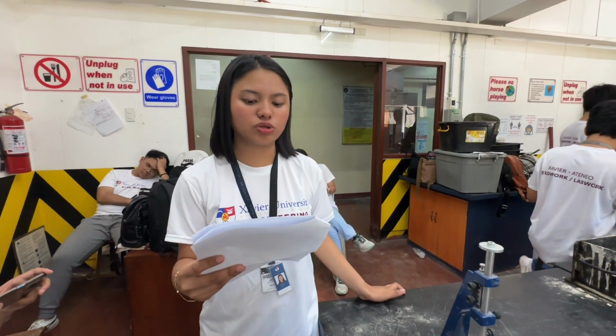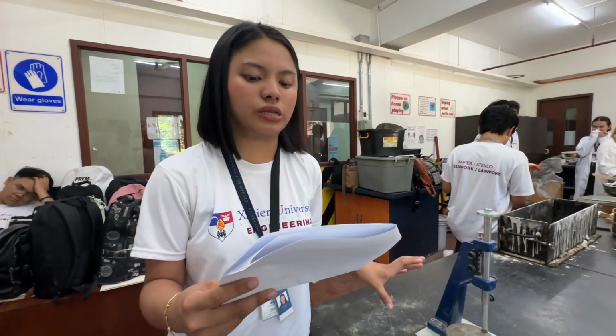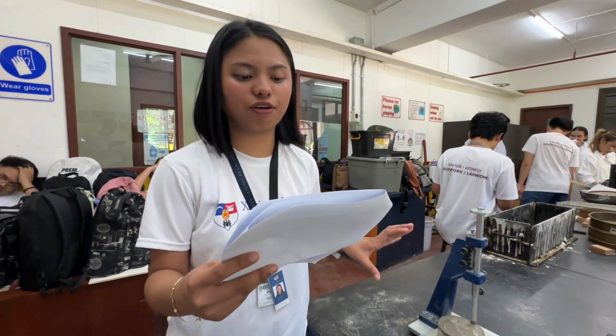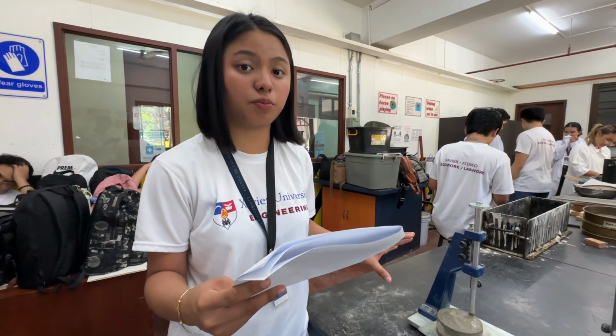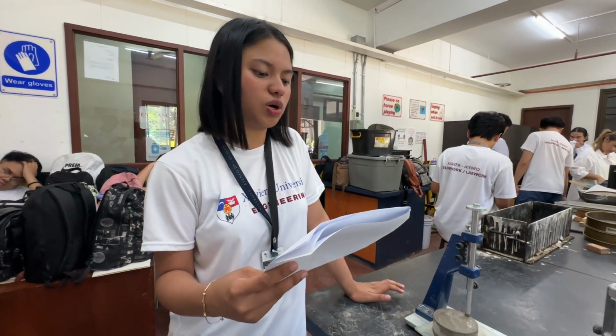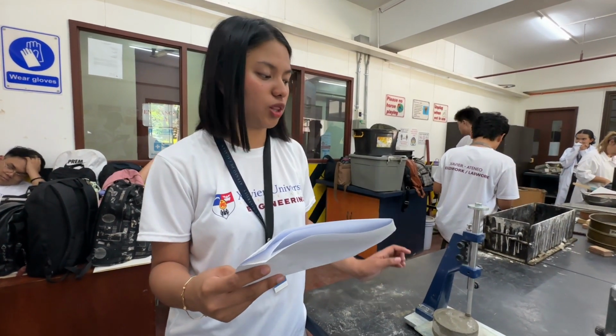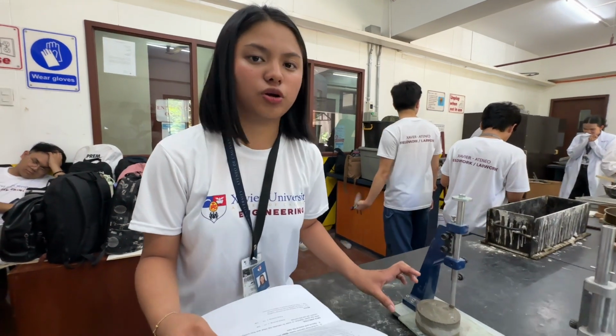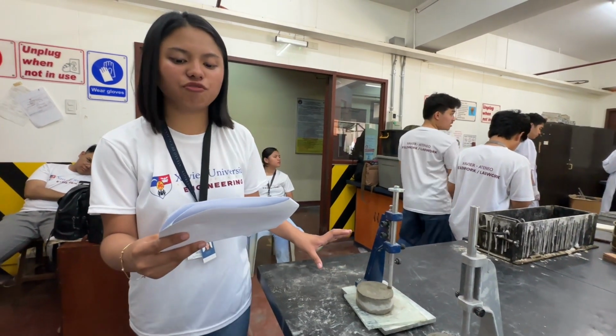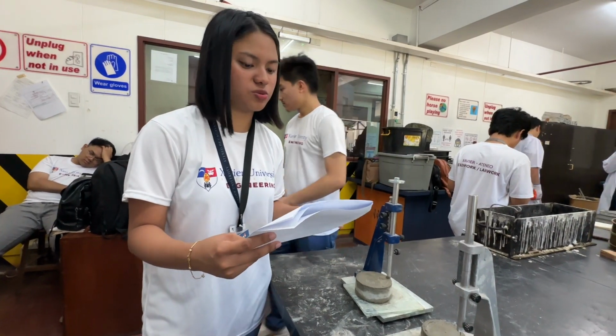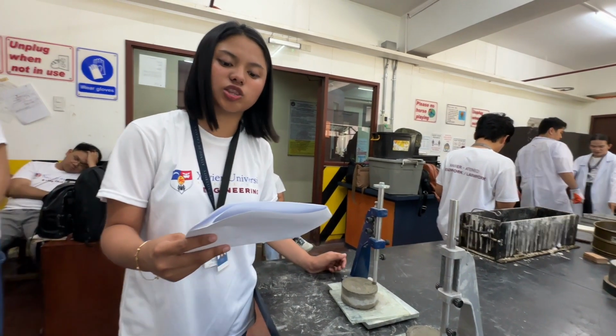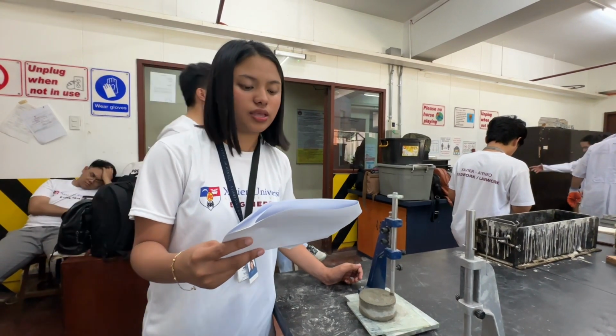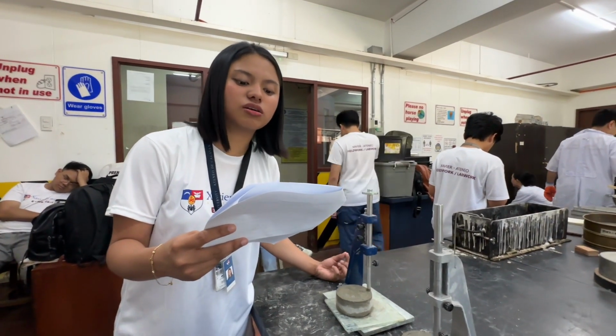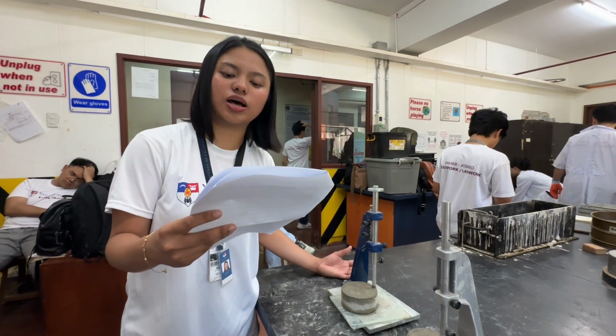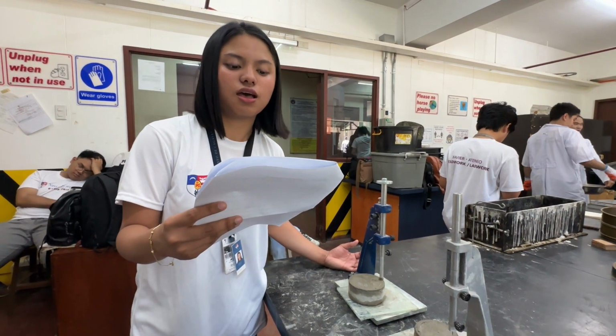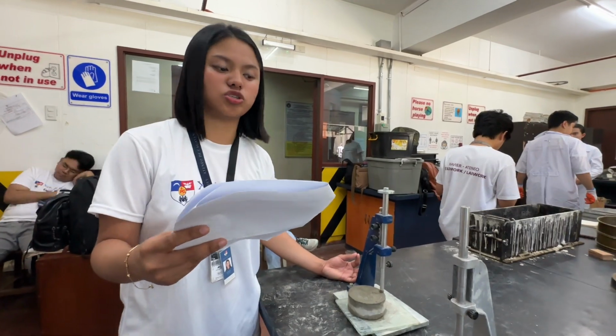So now we're going to determine the penetration of the 1 mm needle at this time, and every 15 minutes thereafter until the penetration of 25 mm or less is obtained. Next, we're going to perform the penetration test by lowering the needle of the rod until it rests on the surface of the specimen, tighten it and then set the indicator at the upper end of the scale. Next, we're going to release the rod quickly by releasing the set screw and allow the needle to settle for 30 seconds. Then take the reading to determine the penetration.